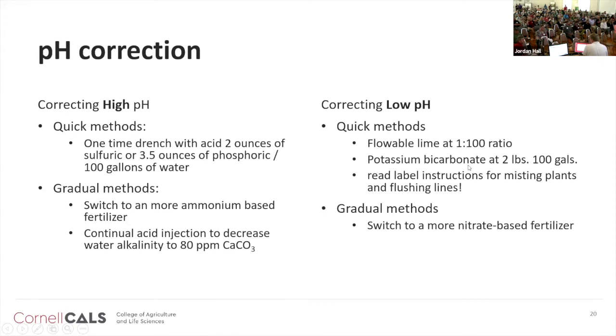Correcting for low pH is less of an issue here. I see it more in places like Long Island, for example, where they have very pure water. We can use flowable lime or potassium bicarbonate. You do want to follow the label instructions very carefully because the flowable lime, if it's in contact with the foliage, can cause a burn to the leaf. So you have to go back afterwards and mist any material off of leaves if it got on them. You also want to flush your irrigation lines after using those materials. A more gradual method is to switch to a more nitrate-based fertilizer.